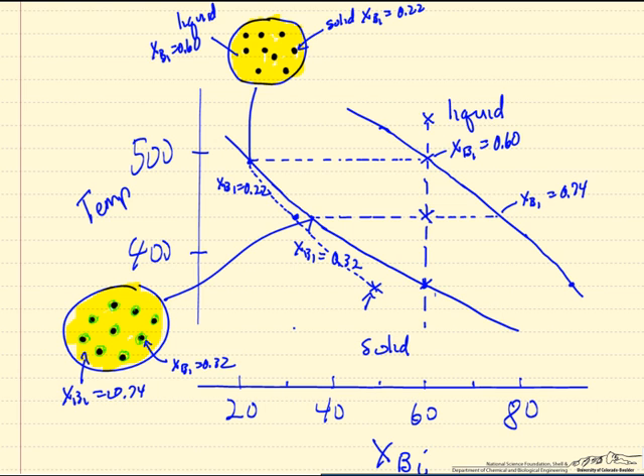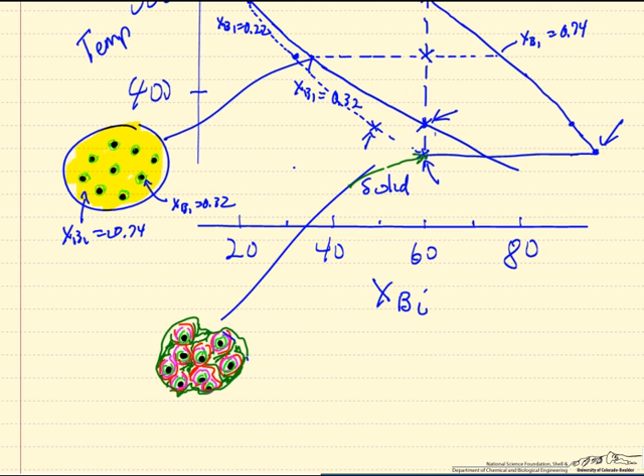Instead, we have a mixture of solid and liquid. When we get to this point where we have all solid, I've tried to schematically represent it. We have a bunch of regions with a gradient, this core structure with shells of different continuous changes in composition.